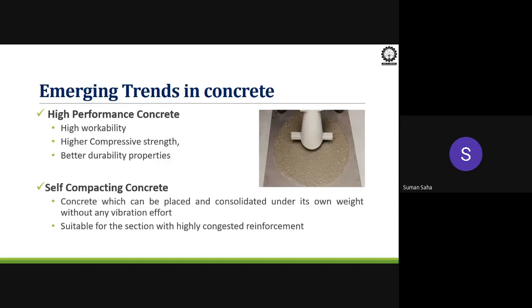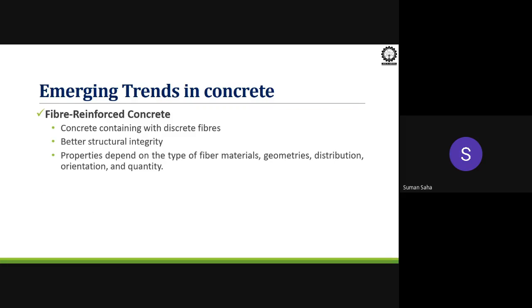without any, you can see there is no segregation or water separation from the concrete, so it can be said to be cohesive. So at the end we need to have at least the compressive strength, which is the main characteristic of the concrete. So it's always very important to notice whether this concrete is getting compacted properly or not by its own weight. If it is not, you may get different kinds of problems when you remove the formwork, some bulging, or in some places voids. So it will create a big problem later on to gain the strength, as well as the durability aspects also. Next is fiber reinforced concrete.